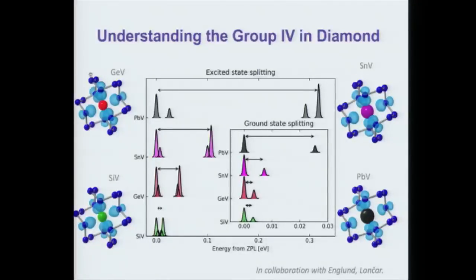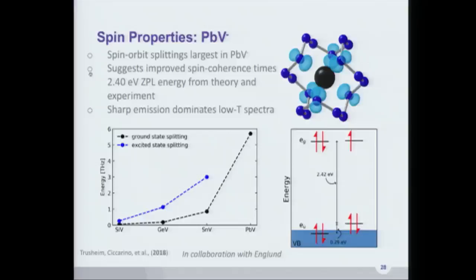And it's very imaginative. You keep going down the same group, and maybe you think about the tin and the lead vacancy center. So the work for the lead vacancy center, order matters. We predicted it, and they measured it. And they measured it exactly where we predicted it. So I was pretty happy about this. This is, again, work done by Chris Ciccarino and one of Dirk's postdocs, Matt Trusheim. So the point with the lead vacancy, in particular, building on the work that people had seen in silicon and germanium vacancy, was that you could get a larger spin-orbit split. This could potentially help improve the spin coherence times. And we predicted the ZPL energy, and that's exactly where the experimental folks measured it, by the way.